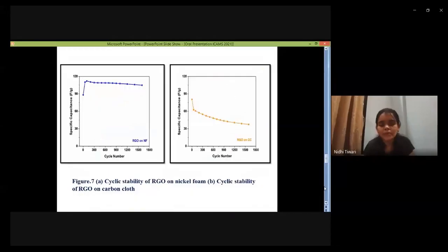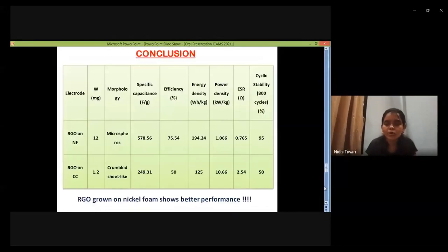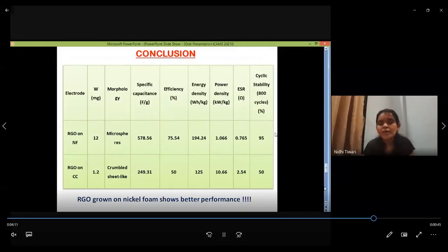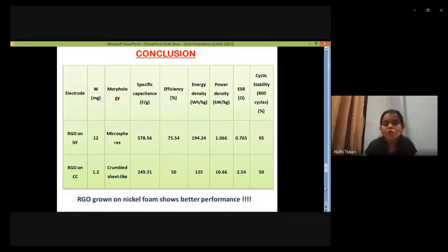Then these are the cyclic stability comparison plots for both RGO on nickel foam and RGO on carbon cloth. Conclusion: you can see the deposited mass is 12 milligram, here it is 1.2 milligram. Morphology is microspheres for nickel foam, and crumbled sheet-like for carbon cloth. Efficiency is 75%, here efficiency is 50%. Cyclic stability for nickel foam RGO is 95%, whereas cyclic stability in this case is 50%. Energy density, power density, all the values can be seen here.